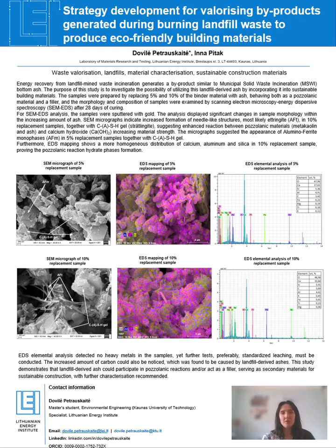And it is also very important to note that the landfill-derived ashes are not uniform materials at all, and their composition strongly depends on the age of the landfill, the types of waste deposited, also the drilling depth and the incineration conditions themselves. For example, ash from older landfills tends to contain more carbonaceous residues and unburned organics, while ash from newer sites may be richer in silicates and aluminates. And these differences influence both the reactivity and the environmental behavior of the material. So in future work, comparing ashes from several landfills could help identify which waste streams produce the most suitable byproducts for construction applications. So what do these results mean?